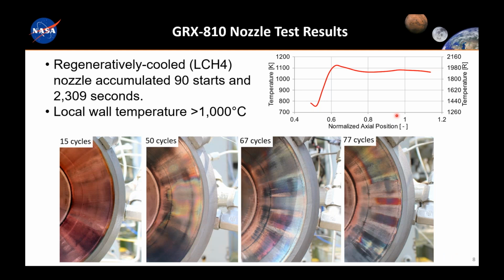Same thing with nozzles. This is an example of a channel cooled nozzle. So you have all of the channels within the component here. You can see the temperatures that we're pushing on this. Local wall temperatures are above 1000 C, and we're running this continuously for thousands of seconds and have accumulated a lot of time on these components. So again, very robust material in these environments.